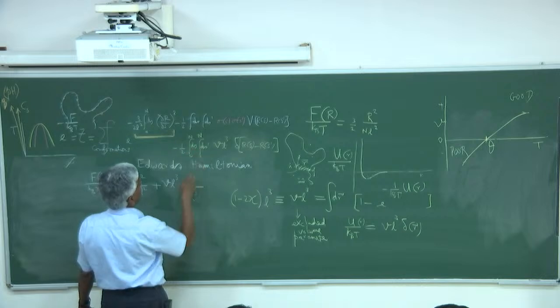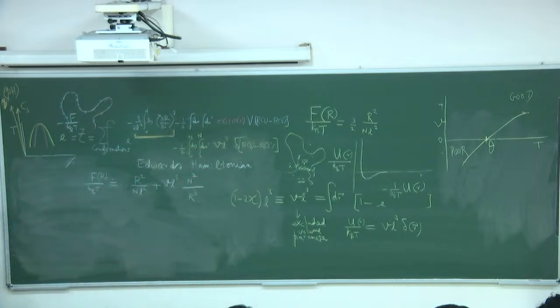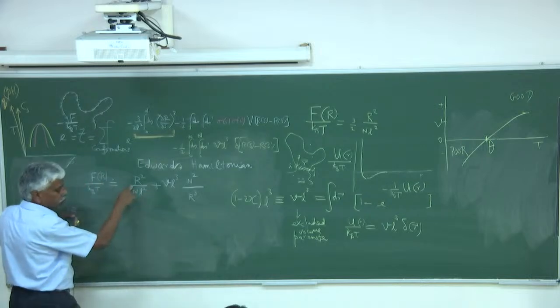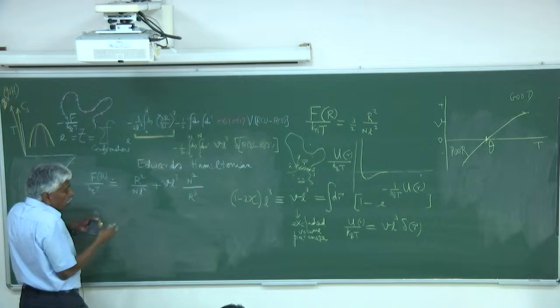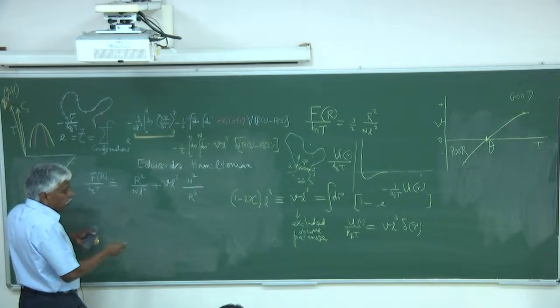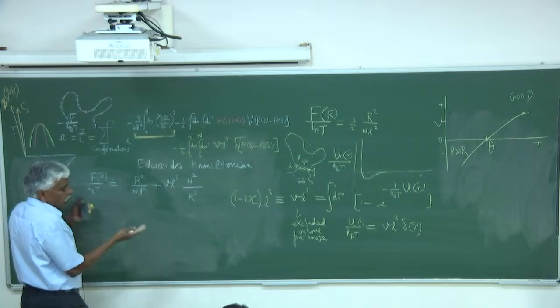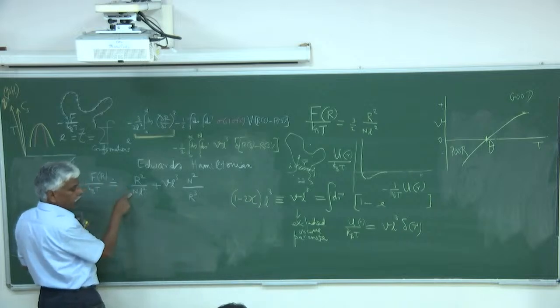The way you optimize this is take the derivative of this with respect to r equal to 0, that is force. If you do this, again I am forgetting about 2r over n, and then here is the negative 3, forget about it, v n squared over r^4, and that is equal to 0. And therefore, when you do this, your r goes like v to the 1/5 n to the 3/5.